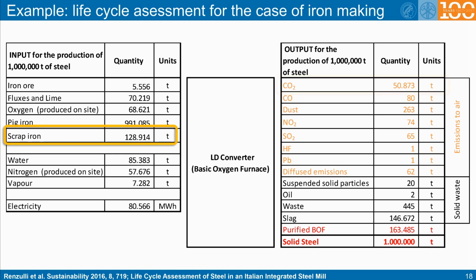On the emission side, it is apparent that particularly the CO2 production in the steel plant is very high. The reason for that is that the pig iron is essentially at the eutectic point of the iron-carbon phase diagram. This means that the pig iron, coming from the blast furnace, still contains substantial amounts of carbon. This high carbon content, which is about 4.38% at the eutectic point, must be reduced prior to casting the material into slabs.